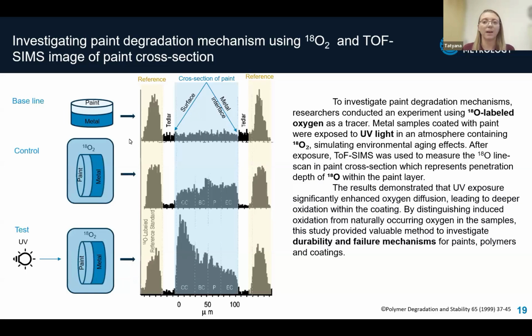For the baseline, they see very low O18 signal. It represents O18 present in nature. The control sample has clearly higher O18 signal as a result of exposure. However, UV radiation significantly enhances oxygen diffusion, leading to deeper oxidation within the test sample.